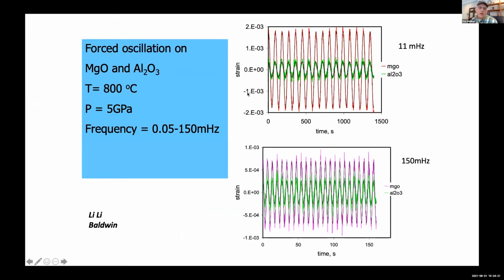One thing that we learned also fairly early is that our hydraulic pumps that apply shear stress were driven by stepping motors, and we can drive them forwards and backwards just as easily. And so what we realized is that we can put an oscillating stress field on the sample, and it can be of varying magnitude and varying timescales, and give us lots of information.